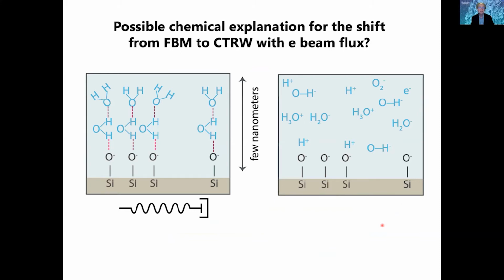Now, ultimately, we would like to have a chemical explanation. Why does the particle experience this? One thing that we think is probably the case, although we haven't yet been able to prove it, is that we create a set of locally charged sites on the surface when we irradiate with the electron beam, in the way that this cartoon suggests, and that those locally charged sites act as the trapping sites for the high flux continuous time random walk. At low flux, the very dense network of hydrogen bonding and the network with the surface of the silicon create a kind of viscoelastic network that makes it a fractional Brownian motion.